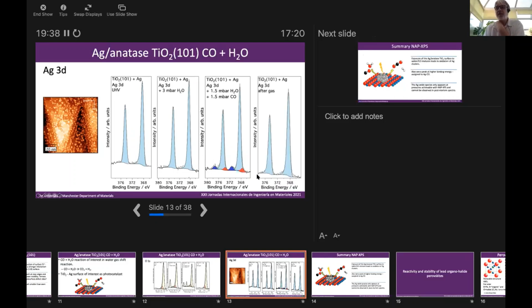When we pump away the gas and look again, the spectrum has pretty much returned to how it was before we exposed the gas. Okay, so there's no real change in the silver 3d. There's no permanent change, and this shows one of the things that makes near ambient pressure XPS so powerful, because if we'd done a classic surface science experiment where we exposed these gases at very low pressures and then returned to ultra high vacuum to measure, then we wouldn't actually see any reaction.